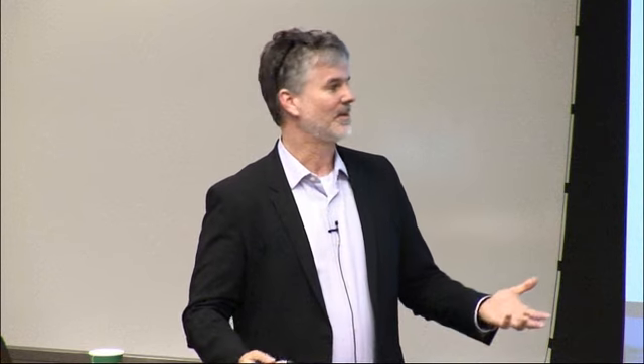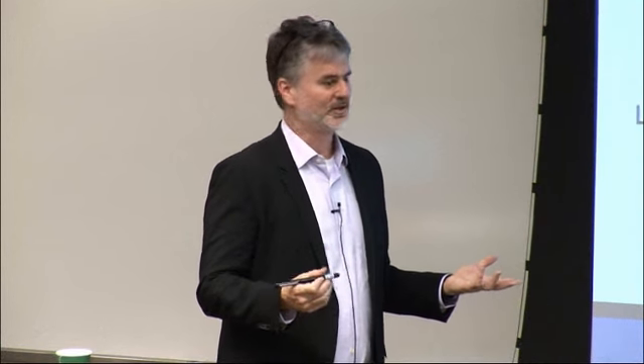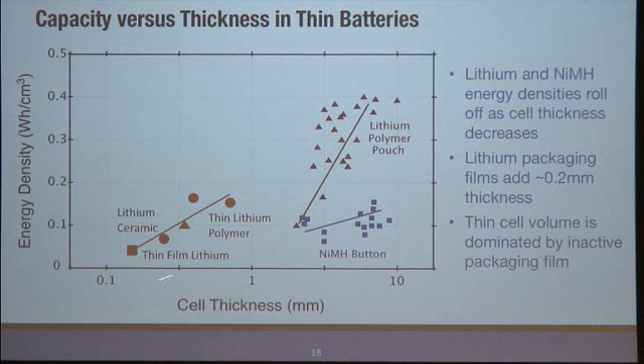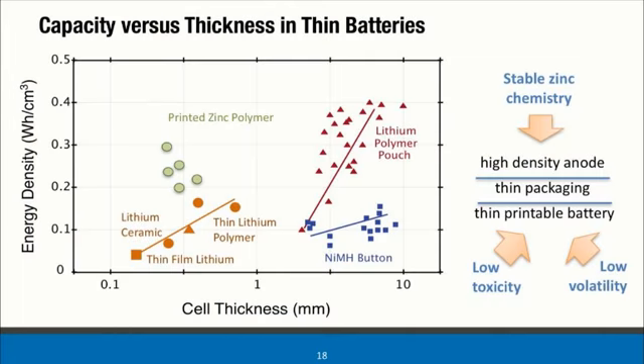As these cell walls, this packaging is hundreds of microns thick. If you want to make a flexible cell, you need to be hundreds of microns thick. You have nothing but packaging. There's no space for lithium anymore. There's no active material space. So actually, the energy density of these things we're talking about for flexible electronics is very, very low. When we move to the zinc system, we can already exceed today what they're doing in lithium polymer.